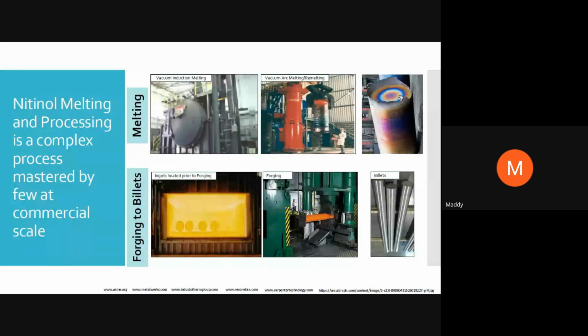And then the ingot is then forged. You can see it heated, and then subsequently it's forged. And after forging, the forged billet is kind of peeled, and the rightmost image on the bottom shows you the peeled billet. So this is how it translates from ingot to billet. And then subsequently, if you go to the next slide, please.